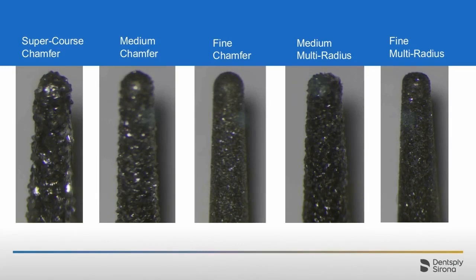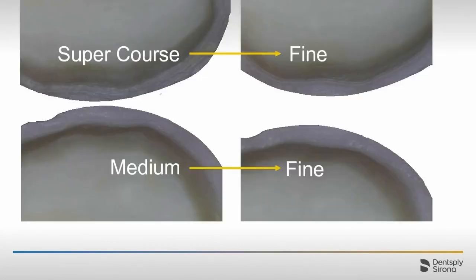We've actually looked at this, and what we realized is if you go from a medium to a fine, it is in fact a little bit smoother. However, if you go from a super coarse to a fine, it's actually quite smooth too. The differences between medium to fine and super coarse to fine are quite negligible, which is good to know because most dentists tend to like to go from super coarse to fine. We've shown in the study that you might have a little bit more scratches, but the margin's still quite smooth. And this is in fact what I generally do.